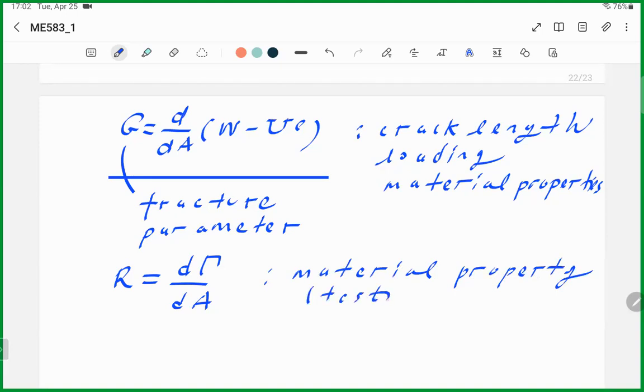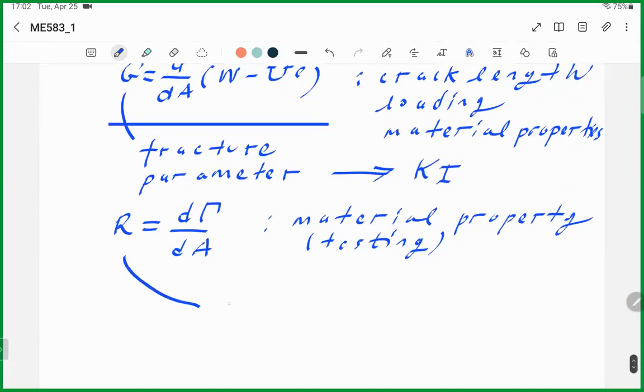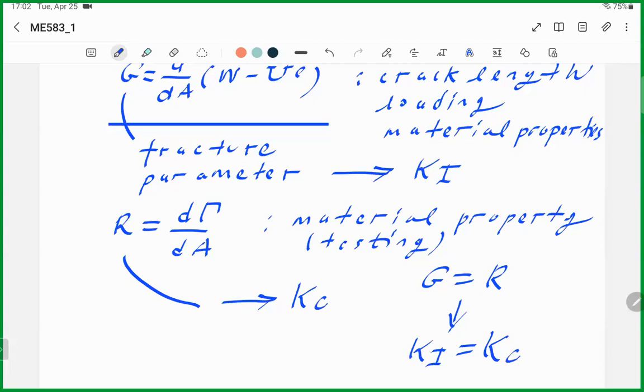testing, and certain factors will affect R, such as temperature, thickness, etc. But these are related. This is related, as we will see later. This is related to stress intensity factor. We can show that energy release rate is related to the stress intensity factor, and R is related to which quantity? It's related to fracture toughness. And this equation, G equals R, is actually the basis of K1 equals KC. If you can show the relations between G and K1 and R and KC, you'll be able to show that this fracture criterion, K1 equals KC, has a sound physical basis, and it's based on conservation of energy principle in general.